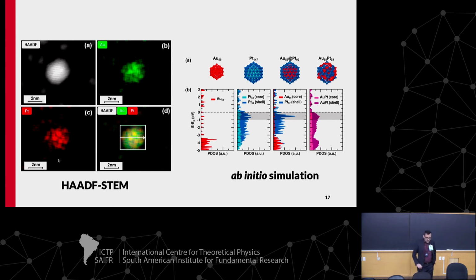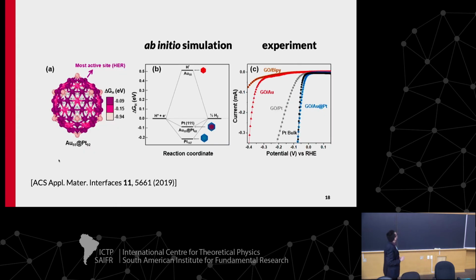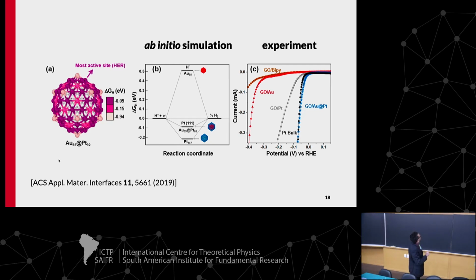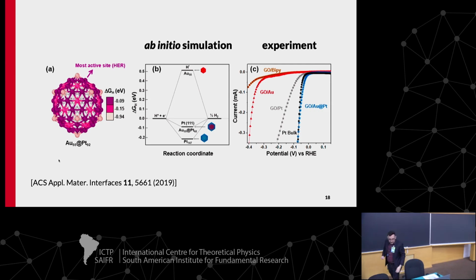When we calculate the electronic properties of these nanoparticles, one thing we compare is delta G. For our core-shell nanoparticles, I have about minus 0.09 electron volts, and this is better than a pure platinum nanoparticle of similar size and shape. We compare this with the ab initio calculation and can see the experiment. We can also see that this core-shell nanoparticle has better catalysis when compared with the platinum nanoparticle.